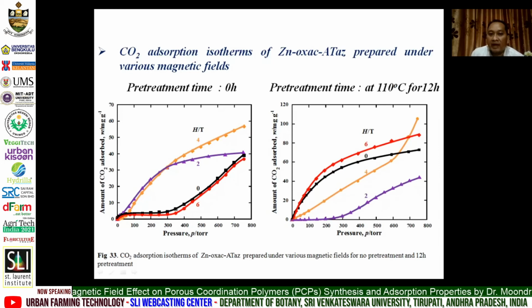which changed the XRD pattern, they can adsorb carbon dioxide in a significant amount. It is considered that the interaction of CO2 and the amine group increases in these 2 Tesla and 4 Tesla magnetic fields. And then after pre-treatment at 110 degrees Celsius for 12 hours, only 2 Tesla can adsorb a slight amount of CO2. Compared with no pre-treatment, it looks like the structure or composition changed because of the heat at 110 degrees for 12 hours.